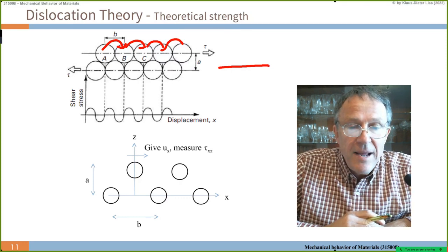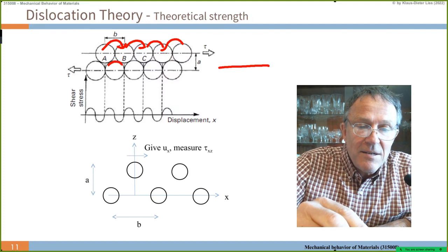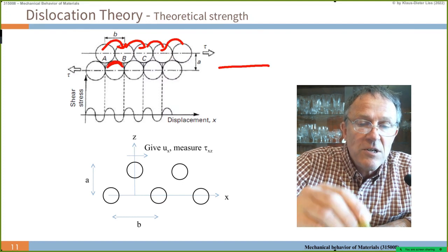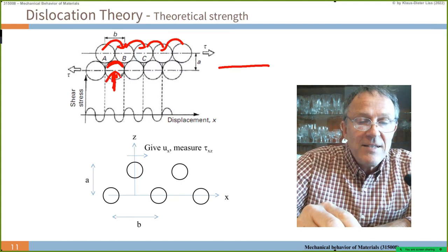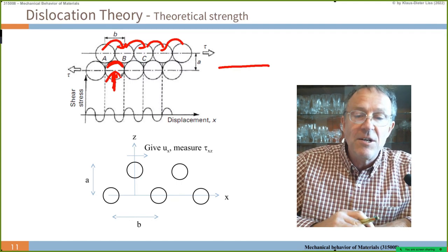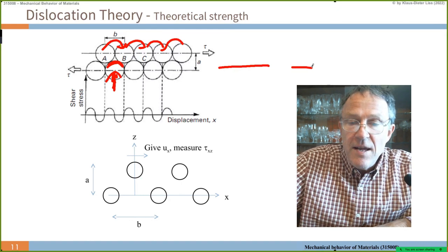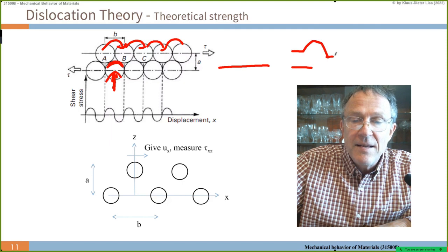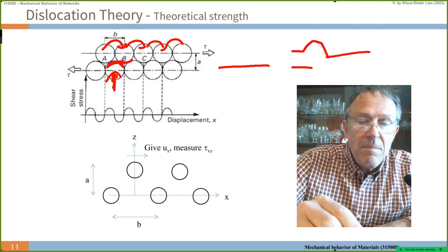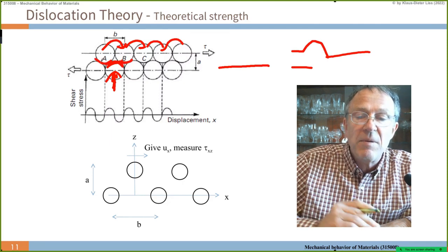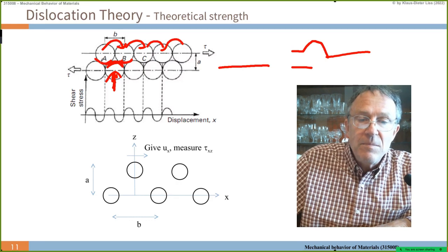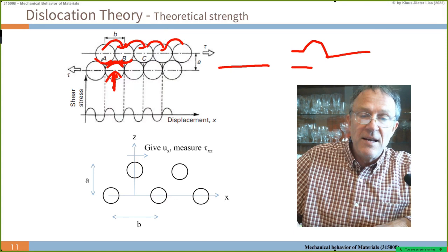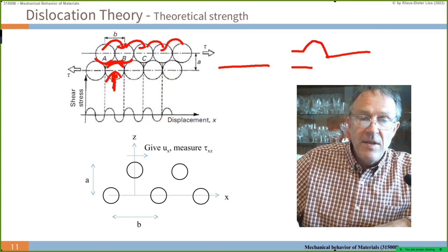That top plane, of course, the A atom has to overcome the potential maximum over this atom, this little potential here. So we need to lift up the upper plane until it locks into the B position. Then the A is slipped from the B. And we have to do that for all the atoms in that plane simultaneously. That's the idea, yeah? So we have stiff planes.